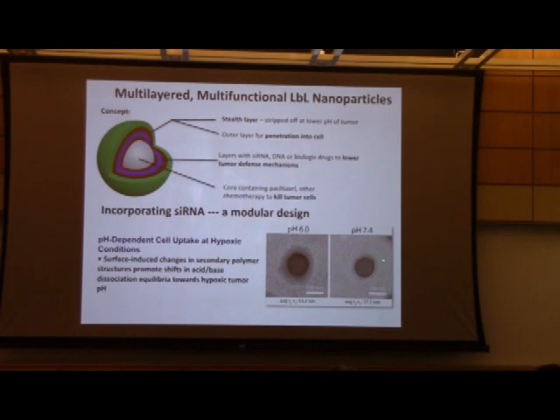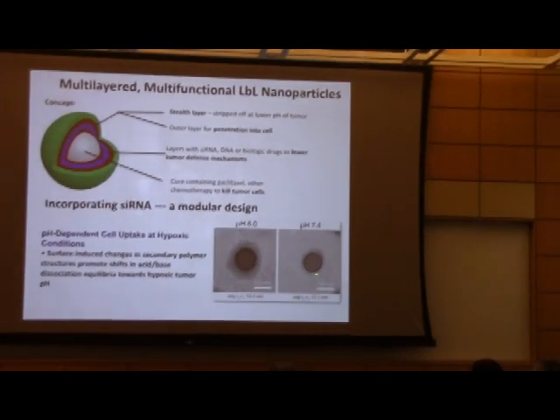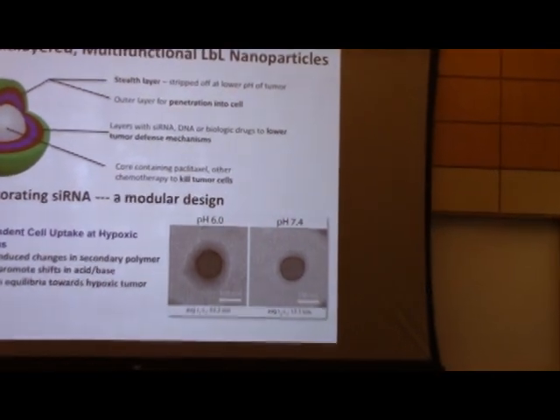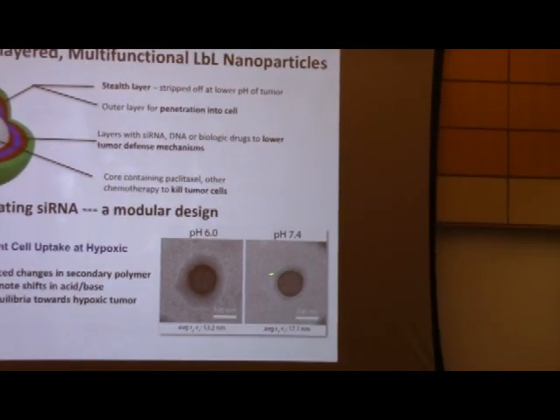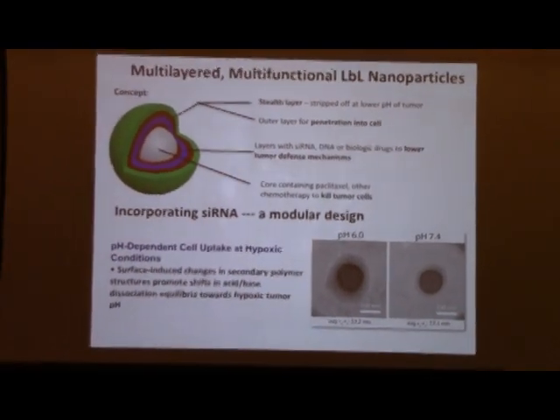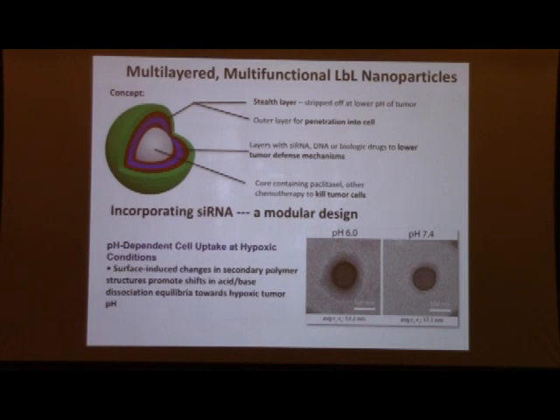In this case, what we're showing is a nanoparticle on the right at pH 7.4, which is the bloodstream pH. And at that point, the nanoparticle is very strongly negatively charged, and it has this core, and hopefully you can see there's a little bit of a halo, a very thin halo, and that's our layer by layer film. This layer by layer film consists of poly-L-lysine. There's a polypeptide that has an amine group, and on top of that is hyaluronic acid, which is a native polysaccharide, glycosaminoglycan, that makes up part of our tissue matrix. But it has a large number of negatively charged carboxylate groups on it. So plus and then minus.